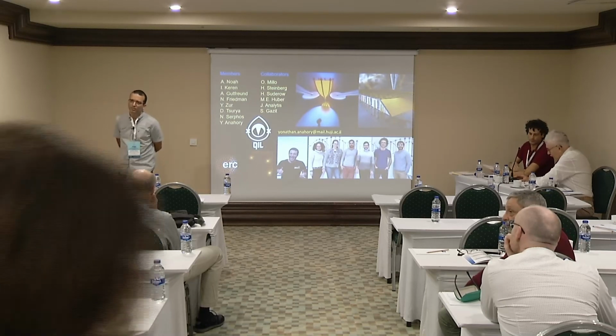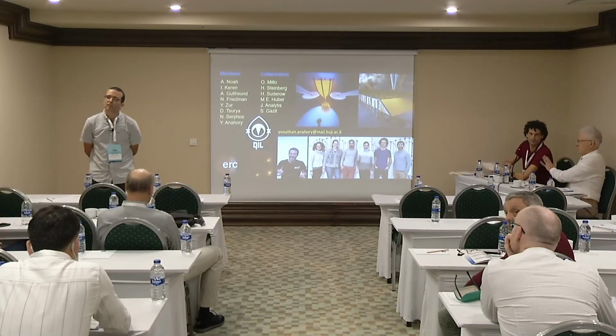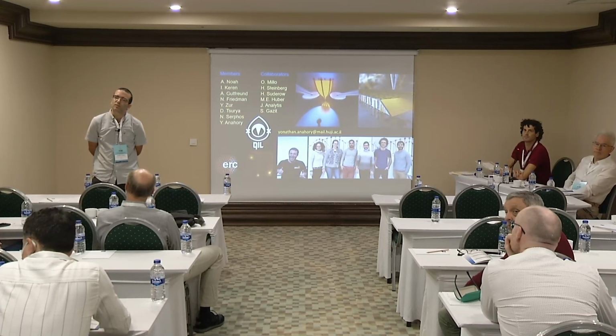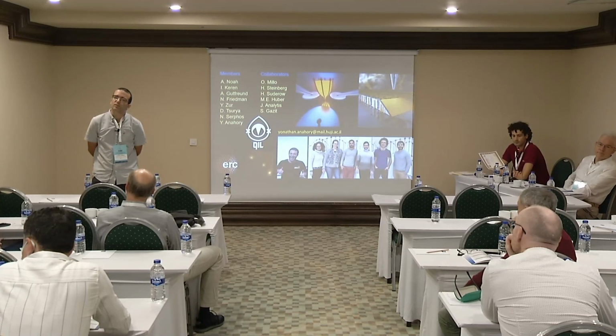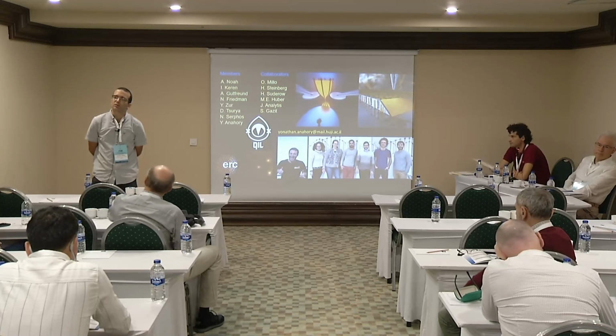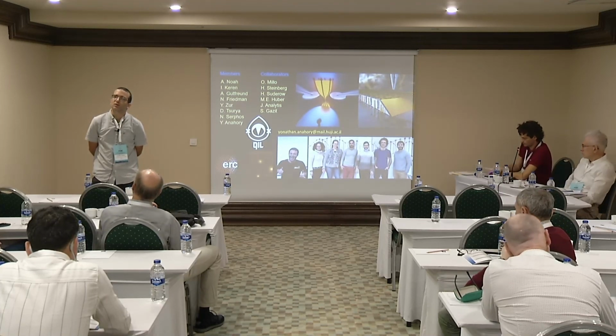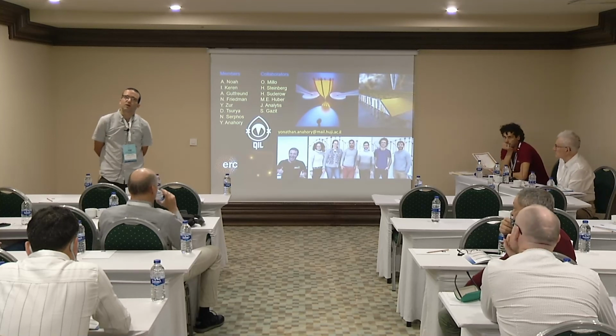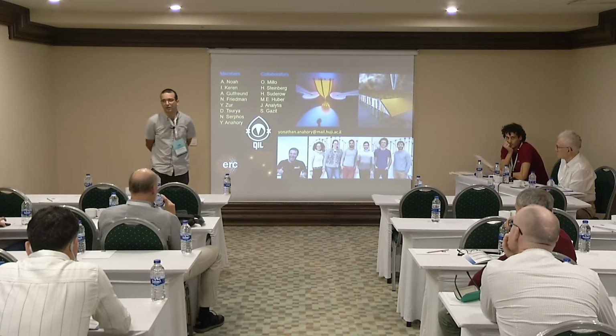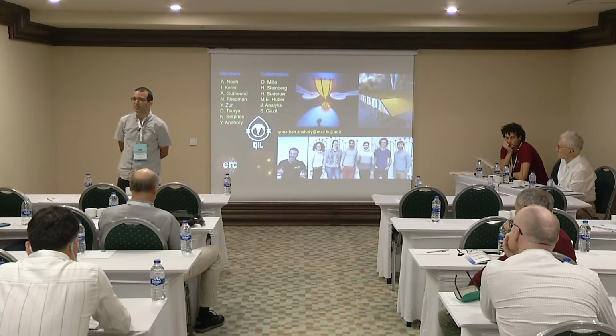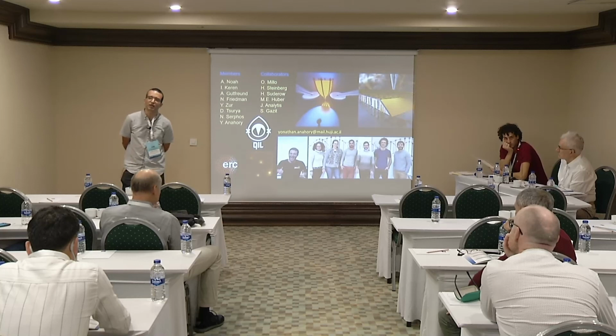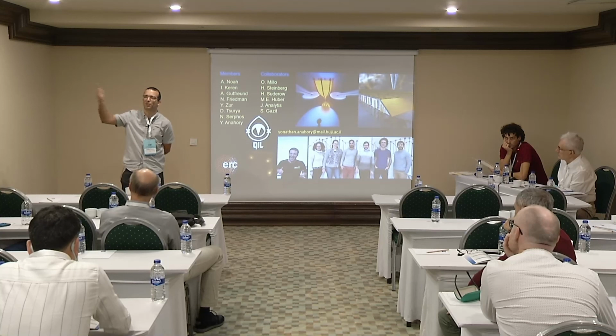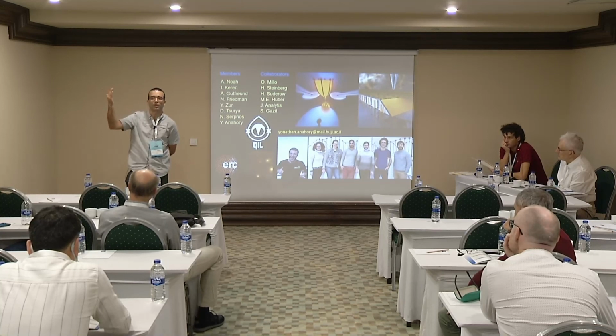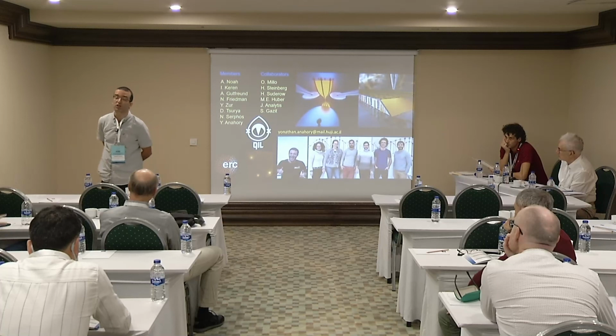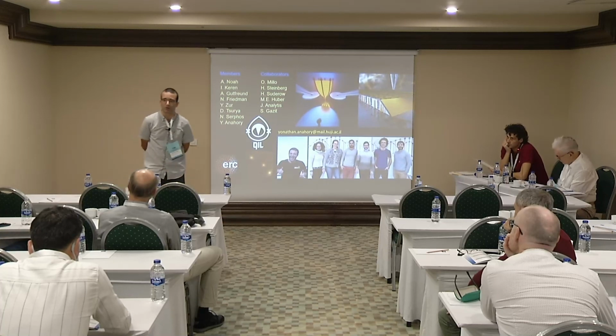And for the magnetic material, as far as I understand, you consider the number of layers at the edges, but oddness and evenness of the number of layers may also have an effect. Have you considered that? We haven't seen any odd-even effect in the interior. It seems that all the thicknesses that we looked at behave the same, but we haven't counted. But you know, unless we always had the even number by magic, then I guess we probe both of them. We haven't seen any effect. It's a ferromagnet, not an anti-ferromagnet. So in that sense.